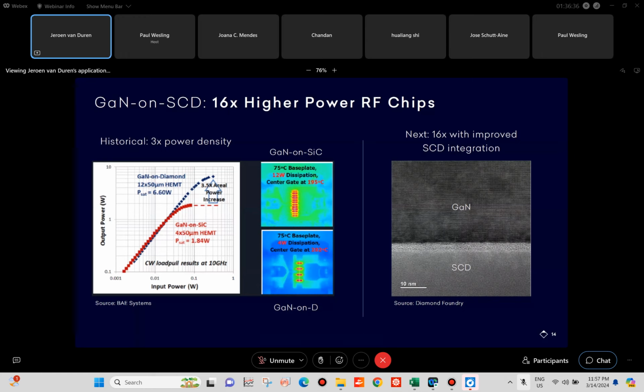However, we're working with partners to get it to 16 times higher than the state of the art, which is about integrating diamond with the latest improvements in both wafer technologies. As you can see here again, you have to zoom in. This is a TEM image of the diamond bonded to the gallium nitride, and you can see again we're talking nanometers when it comes to the interface between the diamond and the GaN.